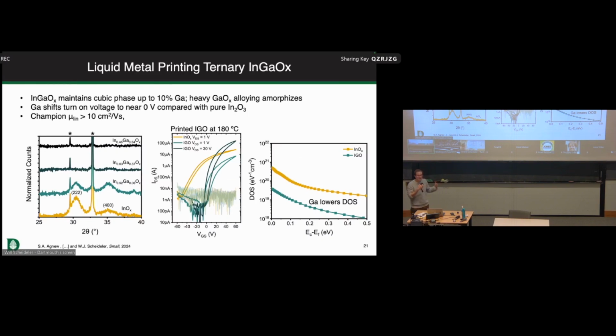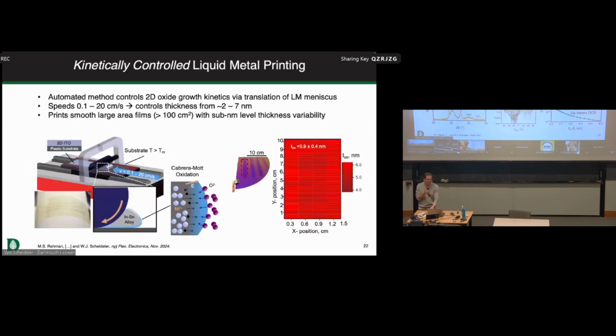The other thing we're able to do is adjust the density of states. The gallium is lowering the density of states, particularly in the mid gap, by reducing the Gaussian distribution of the oxygen vacancies. And then the final peculiar thing that Simon found is that it's still crystalline. Gallium has a different ionic radius. A lot of people before have observed that the gallium tends to amorphize the material. In our case, it remains in the cubic phase, even up to 8 or 9% gallium doping. Okay, so we have doping we can use to control 2D oxides.